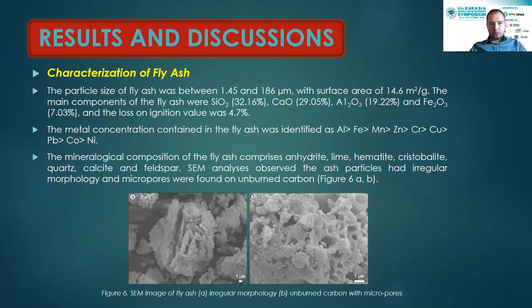The metal concentration contained in the fly ash was identified as aluminum greater than iron, manganese, zinc, chrome, copper, lead, cobalt, and nickel. The mineralogical composition of the fly ash comprises anhydrite, lime, hematite, cristobalite, quartz, calcite, and feldspar. Some analyses observed the ash particles had irregular morphology and micropores were found on unburned carbon.